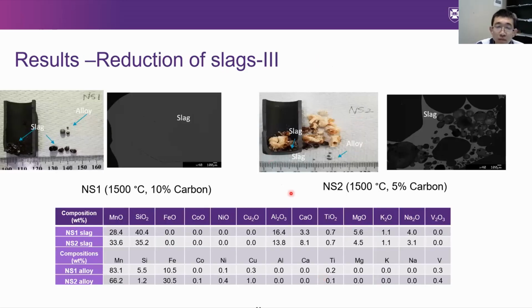So here, again, we carried out two experiments at 1500 degrees with 10% and 5% carbon addition as the reductant. This is done in a graphite crucible. So graphite can also further reduce the manganese oxide slag. The table also shows the slag composition and the alloy composition. So here's a manganese-rich silicon and iron alloy.